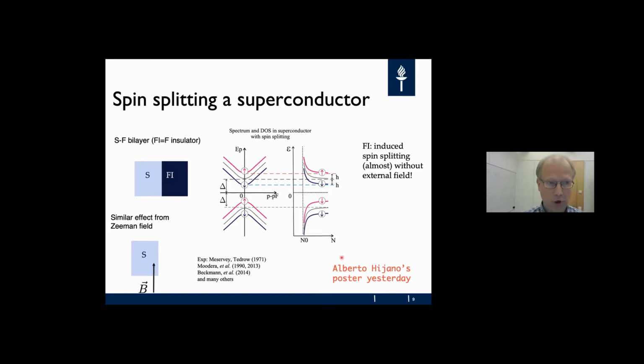So the point of the ferromagnetic insulator here is really to provide the spin splitting almost without an external field, and actually the field scales needed in this ferromagnetic insulator case are usually much smaller than in the case where you do the same with an external Zeeman field.